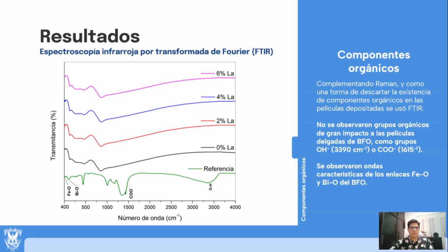FTIR analysis confirmed the purity and quality of the BFO thin films, showing no detectable organic residues like carboxyl, carbonyl, or hydroxyl groups that could compromise performance. The spectra revealed characteristic iron and oxygen bonds and bismuth and oxygen bond vibrations, confirming the expected inorganic structure. The absence of organic contaminants is critical to preserve optimal optical and electrical properties in devices. These results demonstrate the film's chemical stability and suitability for optoelectronic applications. The controlled synthesis ensures impurity-free material for use in solar cells or sensors.